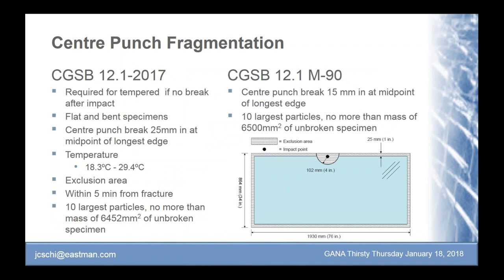The center punch fragmentation test also has not really changed. If you look, there are some minor things with the mass of unbroken specimens and stuff like that, but it's all the same. You punch the edge. The location of the punch is somewhat different. It used to be 15 millimeters at the midpoint. Now it's within 25 millimeters of the midpoint, and then there's some exclusion areas that you don't count for tempered glass that were not necessarily defined in the 1990 version.